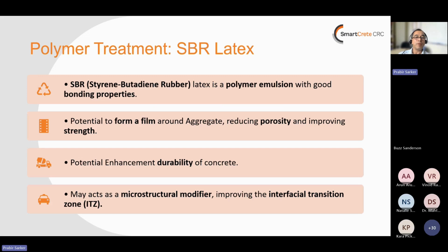So the other method is that Riyadh has been trying. This is still, the tests are going on. So using SBR latex, it's an emulsion, to mix it with the recycled aggregate to get some improvement of the properties of recycled aggregate, improvement of the adhered mortar. So SBR latex is a material which can show some bonding and can show some pore filling effect. So the bonding is important for concrete application, and that's why SBR latex was used.